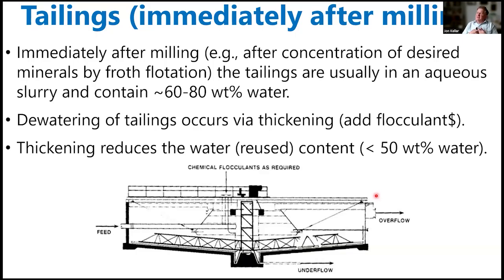So here I'm thinking about the tailings immediately after milling or producing a concentrate, such as froth flotation. The tailings are usually in an aqueous slurry containing 60 to 80 weight% water. And so there's a need to dewater the tailings, reuse that water, and typically that occurs by thickening, where below we're looking at a traditional rake type thickener. We add flocculants to expedite the sedimentation of the particles. The thickening will reduce the water content to usually less than 50 weight% water. And I note that you're adding a chemical here, and that's a cost that is usually paid simply to expedite the sedimentation and the ability to reuse the water.